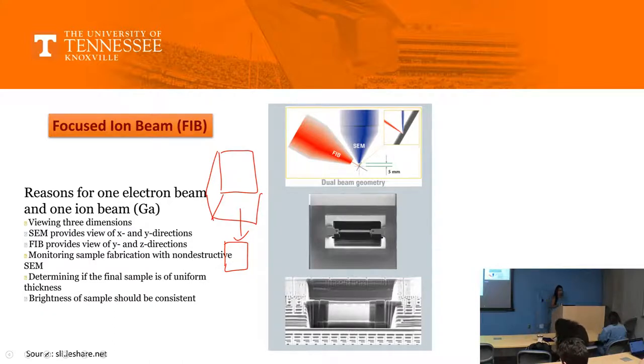So what we do here, we deposit platinum on the center of this small specimen and try to take the desired very thin material in the unit of micrometer. We are not destroying anything as a bulk, right? So this is the top reason, right? And you see here, this is how your sample looks like before people take it out. They try to make it very thin before they take it out from the sample. So this procedure is extremely important to make it thin.